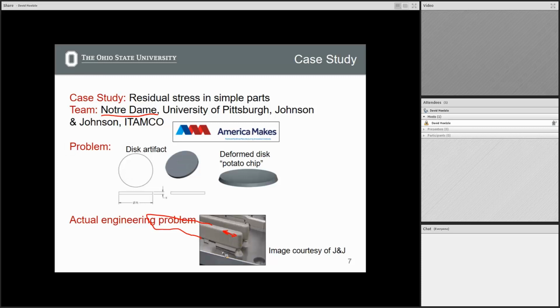So what the engineers at Johnson & Johnson did is they used the normal support structure, which we went through in, I think it was module 5 here, but then they also recognized that they're going to get a ton of residual stress in the part, and so they made these pyramids here that are solid metal. So actually part of the material to hold this down while it's printed, and even then it pulled away. It broke what's somewhere around a 0.5 centimeter structure away from the part, even though they tried to reinforce it. So this is basically the worst thing you can try to do, and this is a very real problem with additive manufacturing.